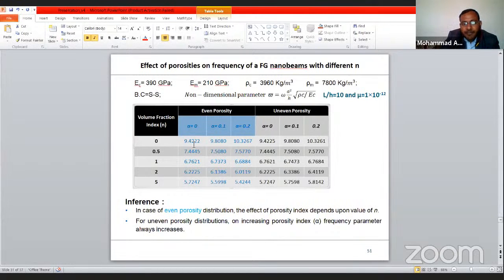is changing. Like for n equal to 0, the effect is increasing, means on increasing the porosity coefficient alpha from 0 to 0.2, the frequency parameter is increasing. But for the higher values of n, volume fraction index, it is decreasing. Whereas in case of uneven distribution of the porosity, on increasing the porosity coefficient alpha from 0 to 0.2, the frequency parameter is always increasing.